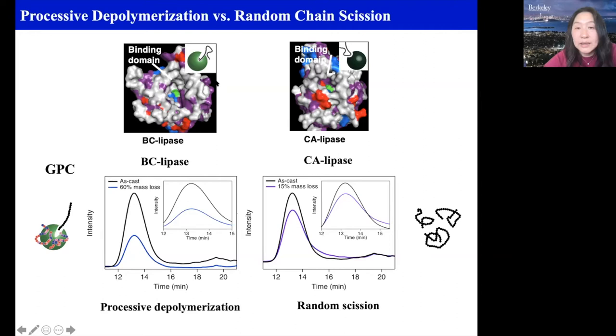We hypothesize that when it's surface exposed, the enzyme binds into the middle of the polymer chain. But when it has a really deep pocket, we are taking advantage of the mobility at the polymer chain end, as well as the conformational flexibility, so that the chain end can get into the deep pocket. While if you're in the middle of the polymer chain, the chain has to bend pretty tightly in order to fit into the space. So the catalytic active site conformation and geometry give us an option to either select the chain end or to dock onto the middle of the polymer chain. And the deep pocket is something that we prefer, because once we know it's the chain end getting into it, the degradation will proceed with depolymerization from the chain end rather than random chain scission in the middle of it.